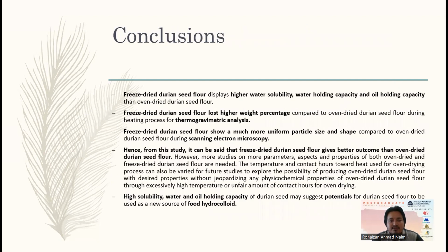For the conclusion, freeze-dried durian seed flour displays higher water solubility, water holding capacity, and oil holding capacity than oven-dried durian seed flour. Freeze-dried durian seed flour lost higher weight percentage compared to oven-dried durian seed flour during thermogravimetric analysis. Freeze-dried durian seed flour shows a much more uniform particle size and shape compared to oven-dried during scanning electron microscopy. Hence, from this study, it can be said that freeze-dried durian seed flour gives a better outcome than oven-dried durian seed flour.